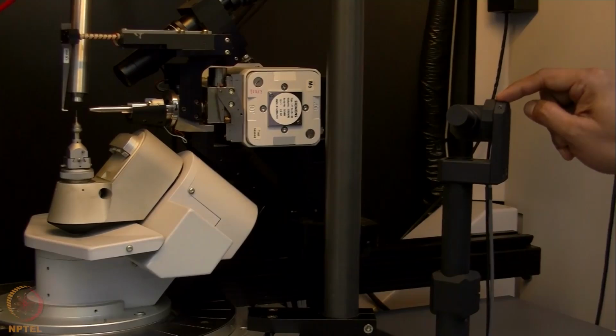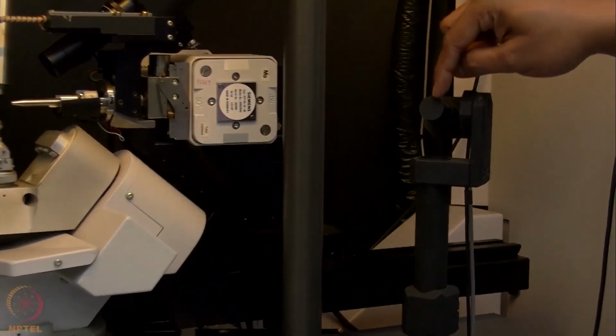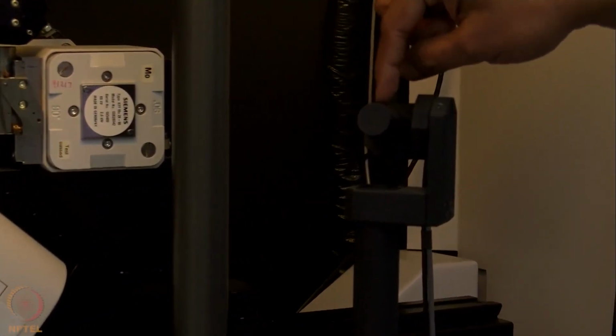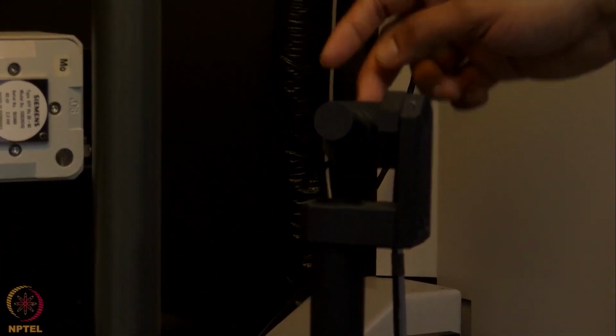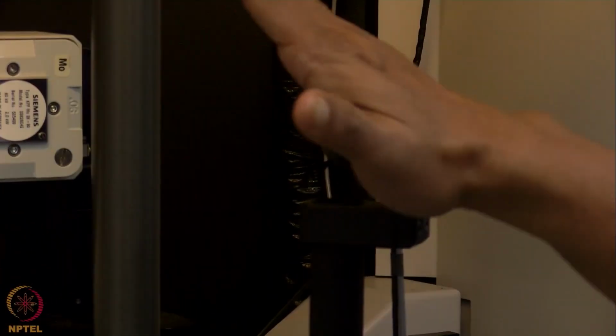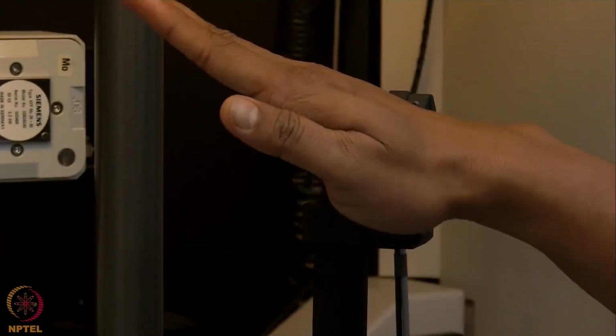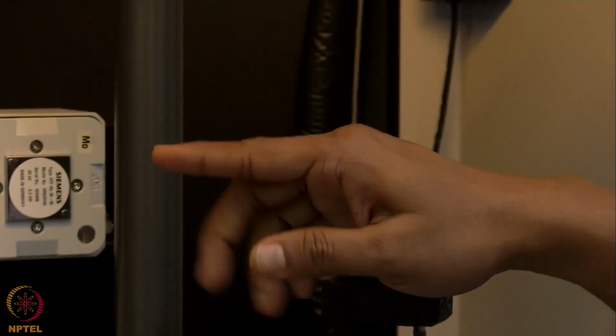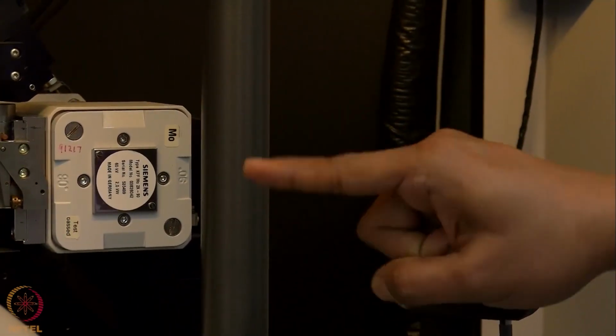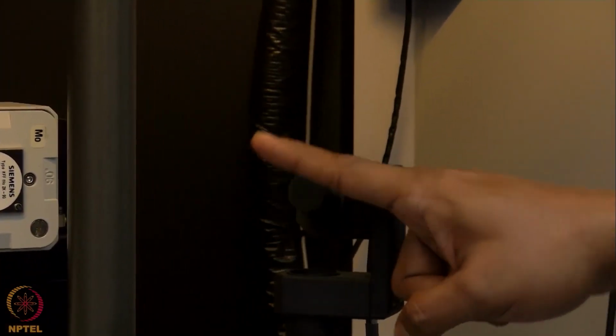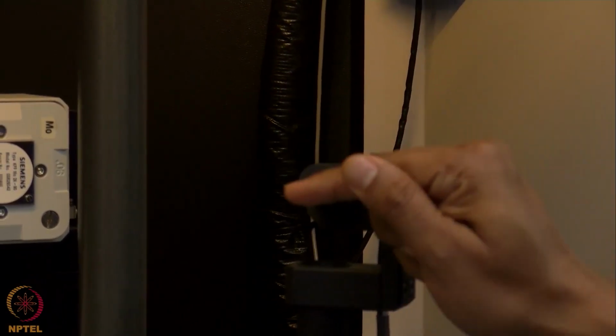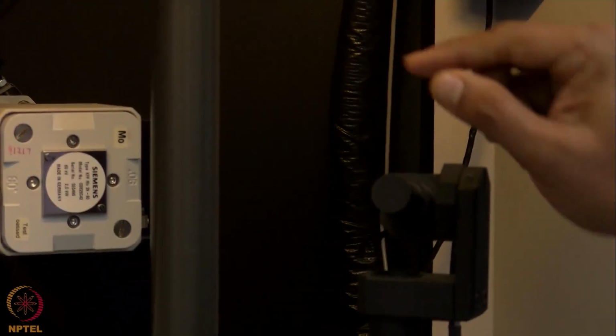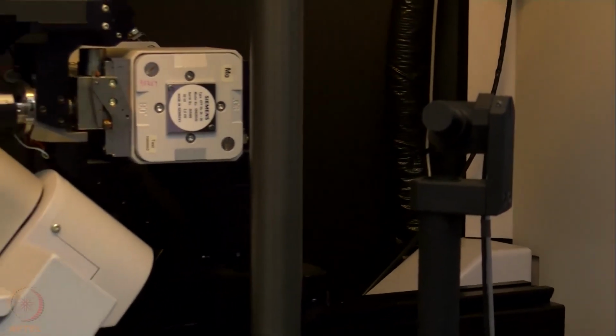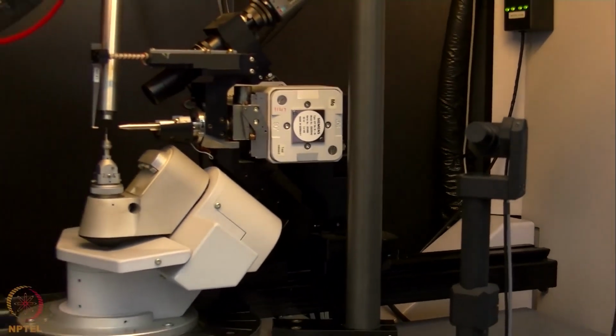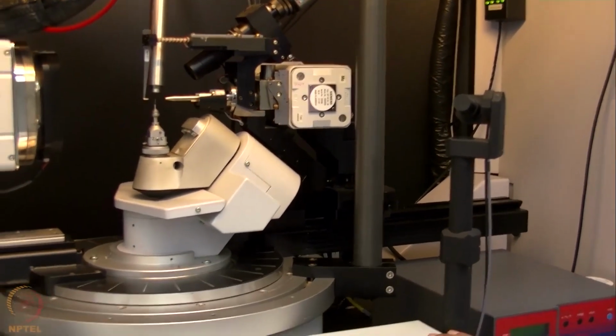So what can then be done is that this particular mirror, which is located here, is connected to a motor behind. So with that motor, the mirror can be rotated very slowly in this direction. When the mirror rotates like this, the beam travels like that. So when the beam travels from down to up of the capillary, the molten zone moves from bottom to top, and the lower zone again crystallizes and forms a single crystal. This process we have discussed in the class, and here you can see this is how it is done.